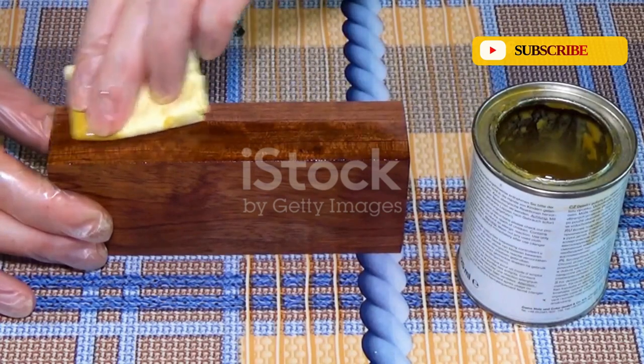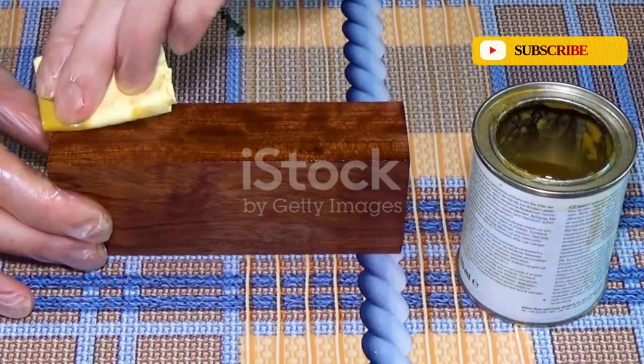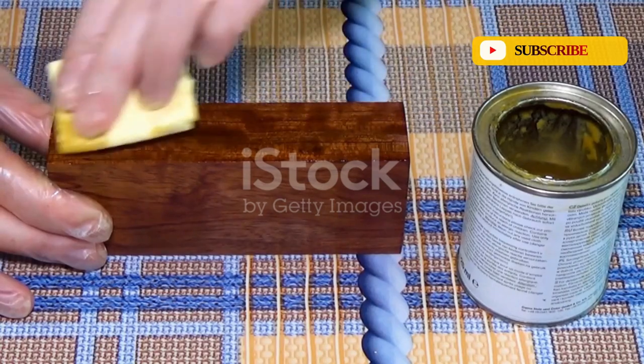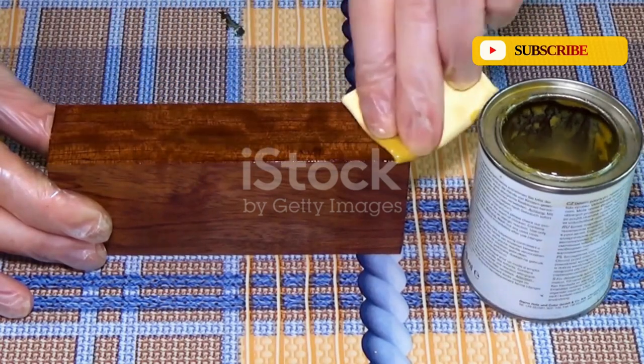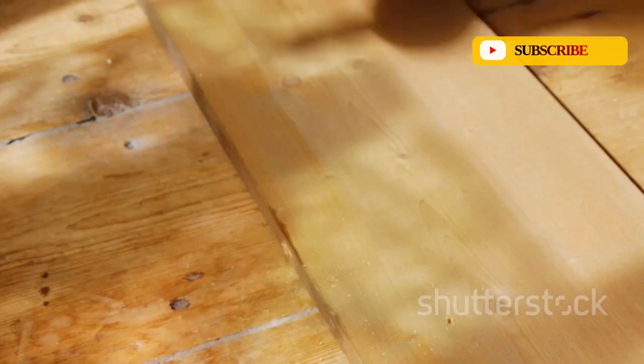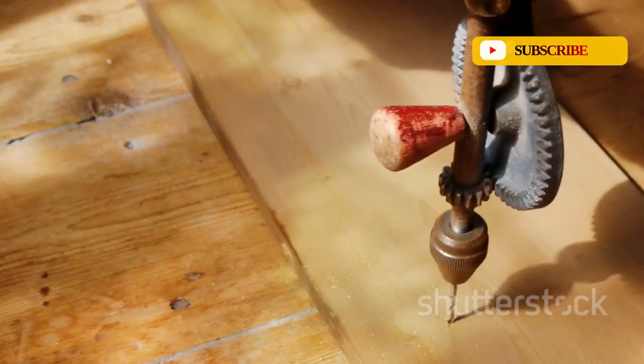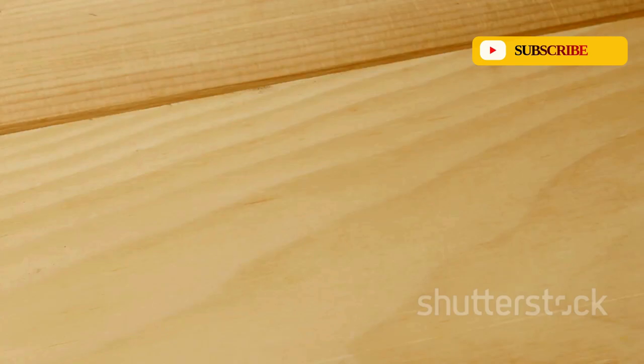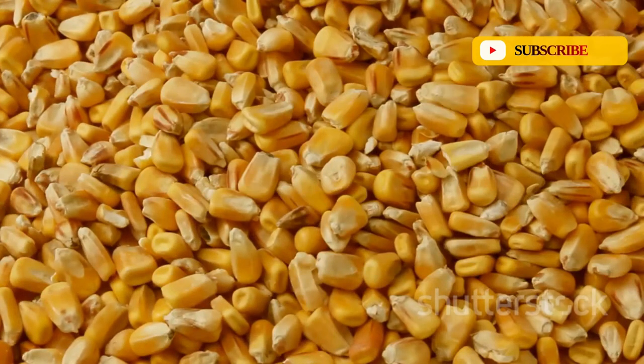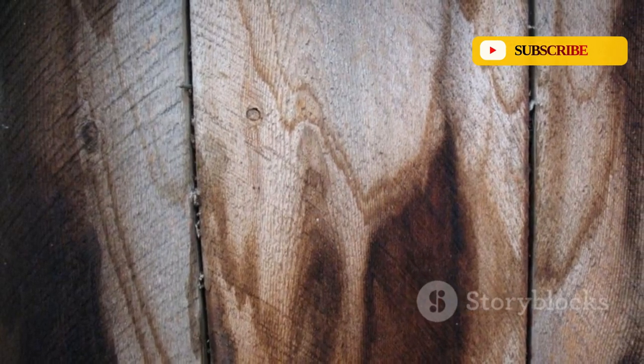The polymerized tung oil provides durability and water resistance from within the wood's fibers, while the beeswax offers a renewable surface barrier. Crucially, this system is microporous. It stops liquid water from getting in, but it allows water vapor to get out. This means the wood can naturally acclimate to changes in humidity without the finish blistering, clouding, or peeling. It's a symbiotic relationship, a partnership between the finish and the wood that respects the nature of the material and is built to endure.